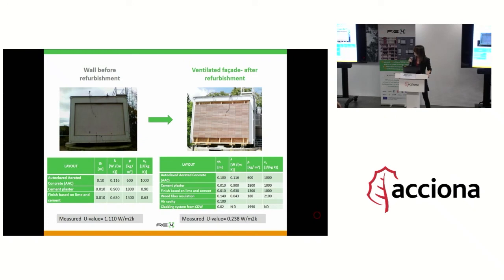As you can see, this wall is currently being monitored, and the measured U value dropped from 1.1 watts per square meter to 0.24 watts per square meter, which is much lower than the value established by the Italian legislation for refurbishment, which is 0.4.